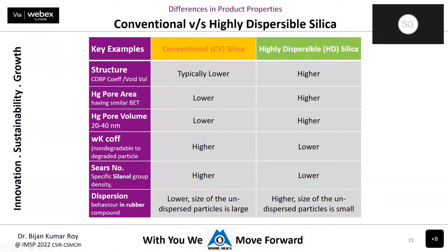If you look at the difference between the conventional and the highly dispersible silica, highly dispersible means it is dispersed well in the rubber matrix. So these are the major properties which play an important role in the dispersion of silica in the rubber matrix. The structure, that is DBP, which is now replaced by DOA, dioctyl adipate absorption. Porosity, that is measured by mercury porosimetry. The coefficient, that is measured through a particle size analyzer. CTAB and Sears number, that is the surface chemistry of silica. Overall it leads to a lower size in the dispersed phase, in the particle size in the rubber matrix, and the size of the particles is lower in the highly dispersible silica.